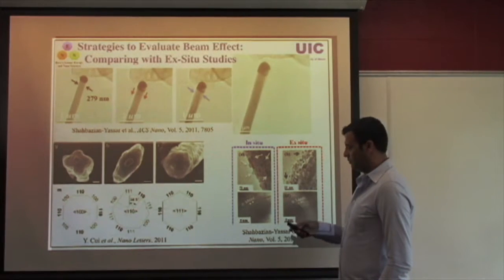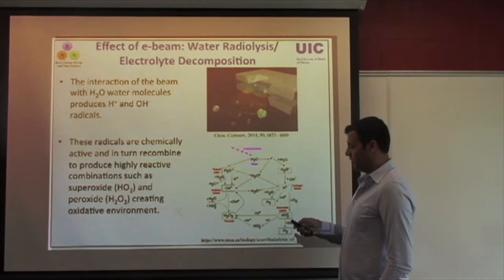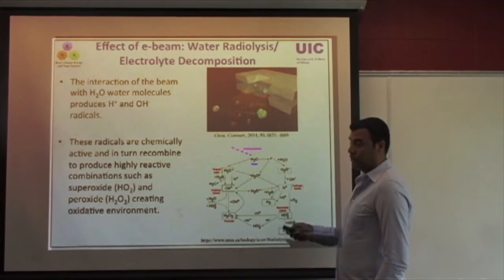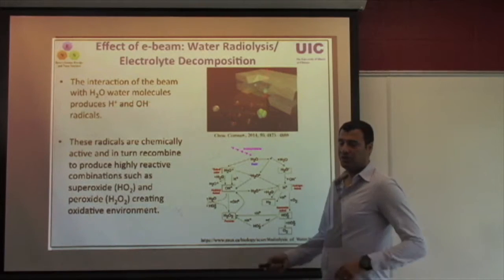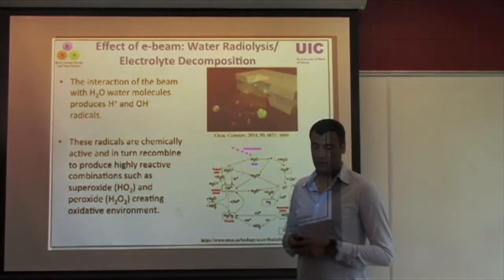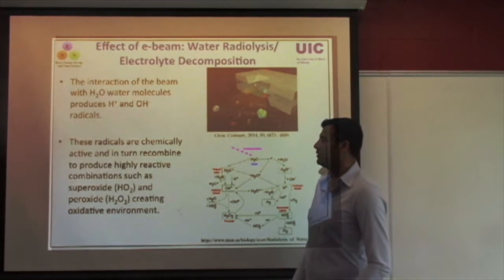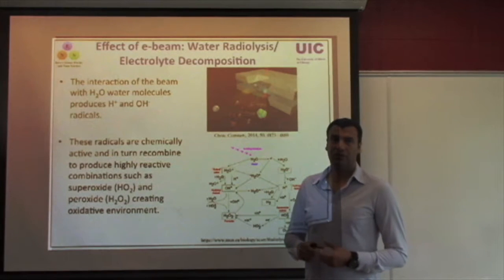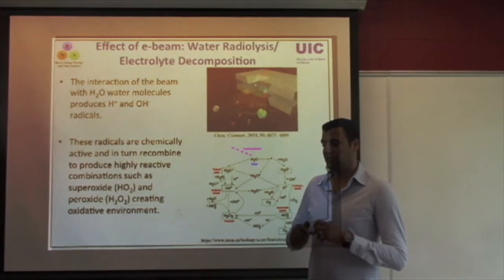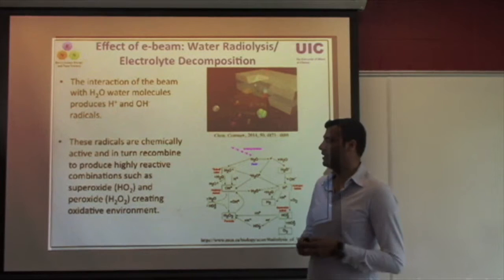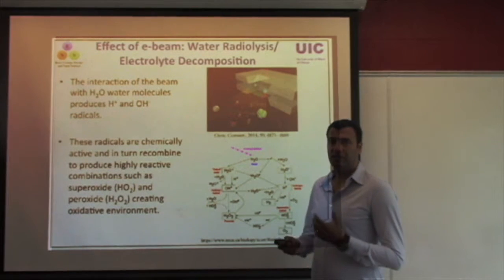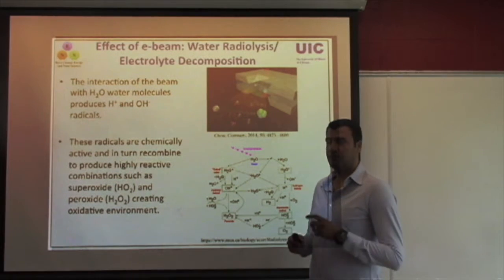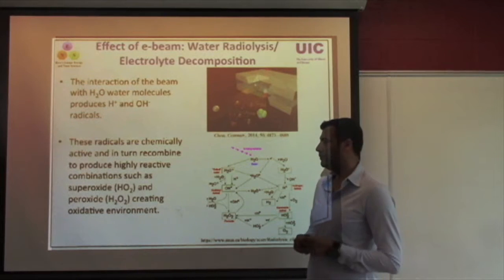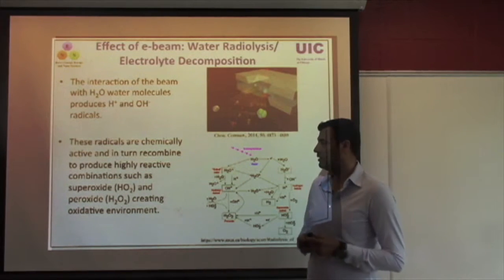So before I go to this slide, I'd like to mention that although there are some negatives associated with this electron beam interaction with your samples, if you are careful in terms of controlling the dose rates of electrons, then you can mitigate or reduce these negative effects on your sample.